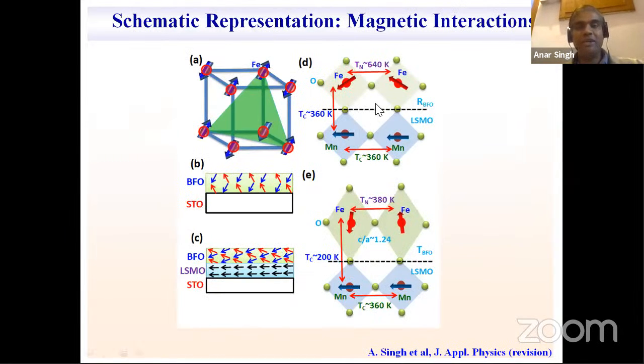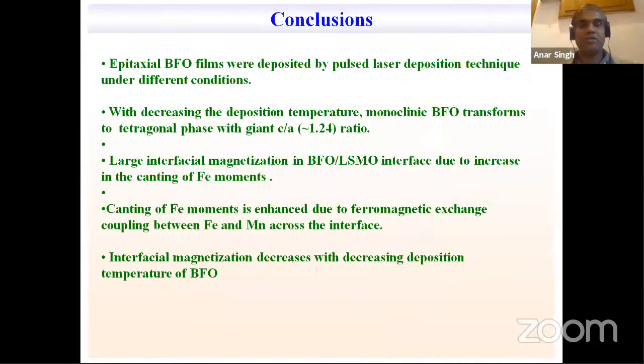So we have significantly increased the magnetic property of bismuth ferrite by depositing that film on a ferromagnetic layer. And this enhancement is coming because of the double ferromagnetic coupling between the Mn and Fe ions near the interface. So this heterostructure could be a material to make some device based on the magnetoelectric effect. This is the conclusion of my talk, where I just want to highlight that the ferromagnetic component of bismuth ferrite has been increased significantly by depositing this multiferroic compound on a ferromagnetic layer.